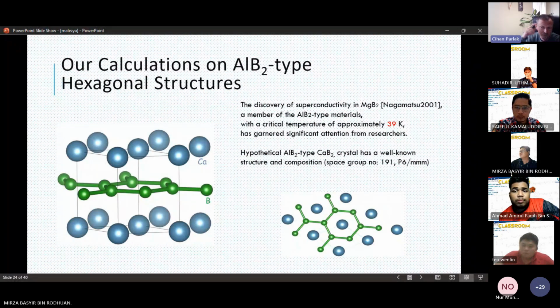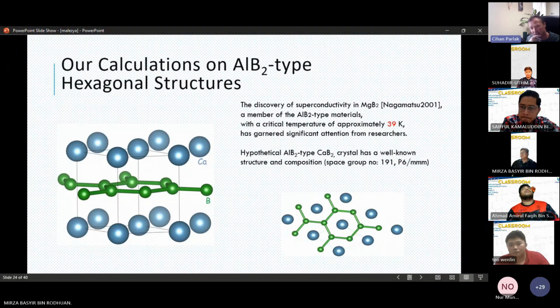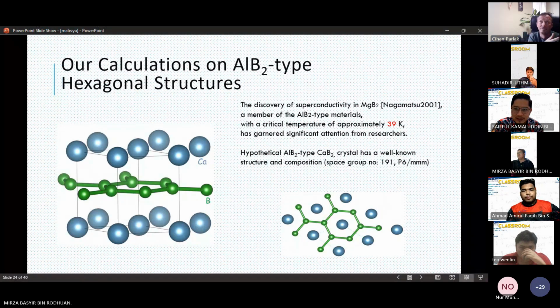But if you look at calcium boride structures, you will mostly see calcium hexaboride, which is also a superconducting material. Maybe it's hard to synthesize aluminum diboride type hexagonal calcium diboride. Maybe the system easily moves to calcium hexaboride, and when you try to make calcium diboride, you will get calcium hexaboride. I don't know the experimental steps of this, but it's hypothetical for now. Next slide, please.